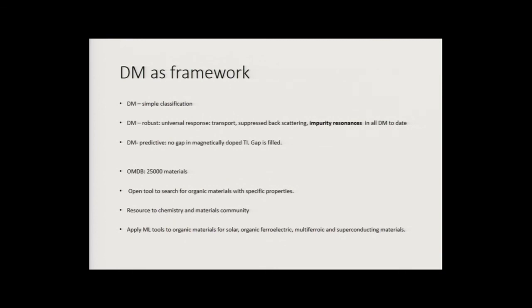Yes, you probably can excite these resonances with electromagnetic radiation, like terahertz radiation. So that would be one. You're talking about observables. First of all, you can see them in STM, but another place where it might be very useful is electromagnetic radiation. And the third one I find is that they come in inherently at the particle-hole asymmetric excitation near the chemical potential if you have a fully compensated state. And so they will probably provide a very large contribution to thermal transport, because the holes and the carriers will carry different, you have a very different conductance for electrons and holes.